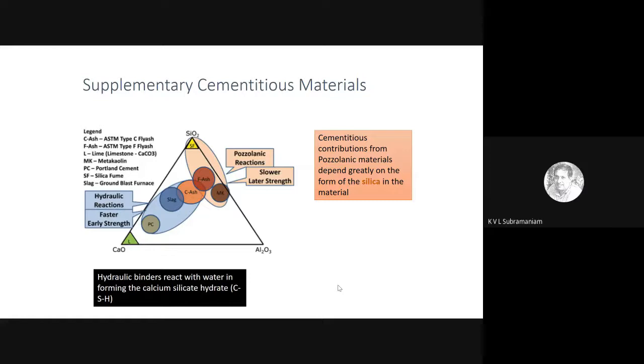And if you look at it, our Portland cement, which is this grayish circle PC, basically is sitting in the calcium-rich corner. The fly ash, which is the maroon circle, is sitting in the silica-rich corner. Silica fume is pure silica. So that is sitting in the corner, which is basically marked as SiO2.